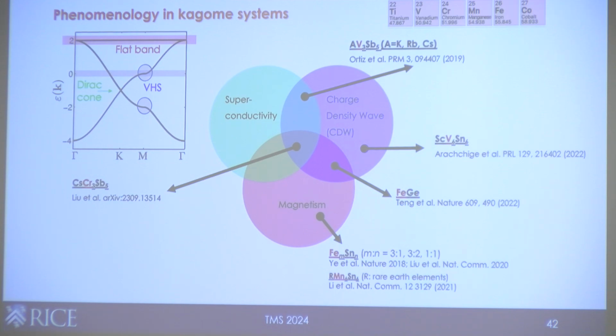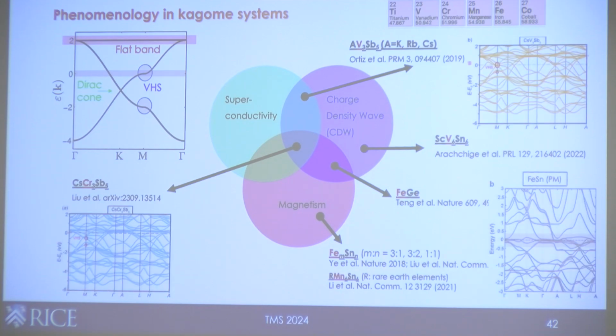So the kagome materials, this is one way of tuning them. And I'm going to show the way this affects the band structure. I know this is a very busy spaghetti plot, but if you stare at it for 5 minutes, you will start to see features that look somewhat like this tight binding calculation of the flat band plus the 2 dispersive bands, right? That's the blue things to highlight, and then the other important thing is where the Fermi level is, right?